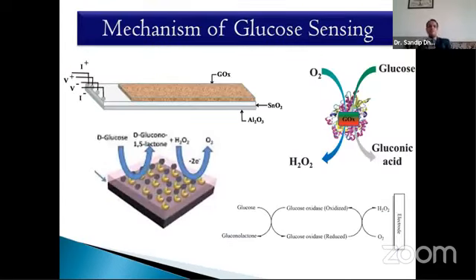So here, this is my work actually, of glucose sensing. We have deposited SnO2 nanoparticles or thin film of SnO2 on an alumina substrate. This alumina substrate is porous, and then we immobilize glucose oxidase enzyme. See this, if glucose oxidase enzyme is not there, we cannot sense the glucose which is present in a diabetic patient. So what we have done, we have immobilized this GOX, that is glucose oxidase enzyme, or you can simply say we coated this GOX enzyme on the surface, and then after functionalization, we put glucose with different concentrations on this assembly, and we tested the resistance of this sensor by using the four-probe resistivity method.